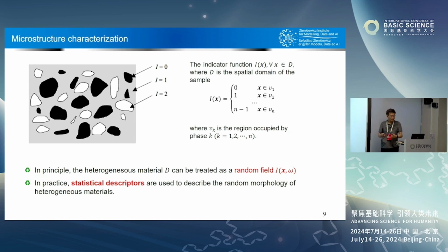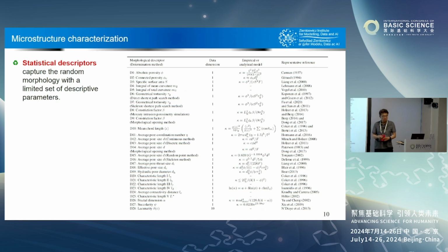microstructure and its morphology. So what are statistical descriptors? The easiest one would be volume fraction. So you might say, I have three phases, black, white, and gray. Each of them counts 30% of my material. That is volume fraction, right? That's a useful thing to know. You might even say, okay, 2-point correlation. So finding 2 points of material within the same phase or within different phases, the correlation between them. So you can do many things like this.